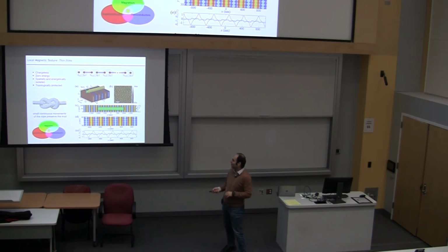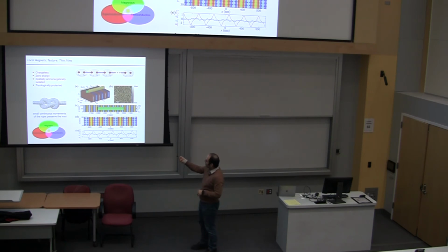So we have actually started a big collaboration on how to add magnetization to this. So now we are making these films. These are cobalt platinum films that go below the quantum well on indium arsenide. And by applying a magnetic field, you can actually break down isotropy. I mean, ideally, I wanted this to be parallel lines. So that's what the simulation is for. But you can imagine if I put the nanowires, it's going to be kind of periodic, right? Because nanowire is a small dimension.